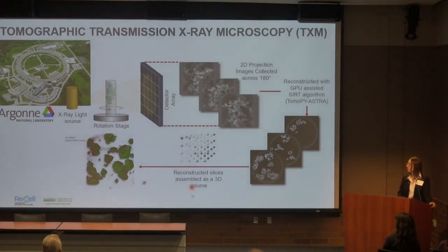So here I'm pulling in some of the work that I did in my PhD using a higher resolution imaging method called tomographic transmission X-ray microscopy. This is a fully non-destructive three-dimensional imaging technique where we can analyze both the internal and external morphology of these cathode materials, as well as elemental composition and oxidation state heterogeneity, using the Advanced Photon Source at Argonne National Lab. So basically you can select a single wavelength of light, then you can analyze the elemental and oxidation state composition. Basically, we take X-ray projection images across the XZ and YZ planes as our material is being rotated. And from that, you can reconstruct your cross-sectional slices shown here.